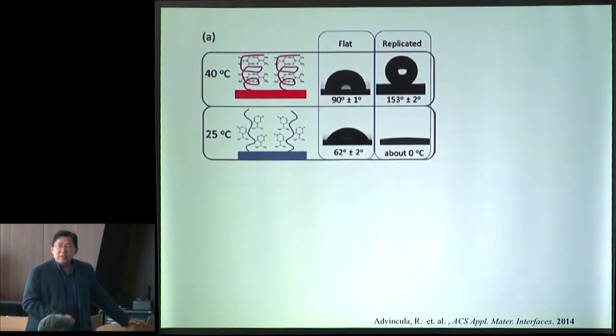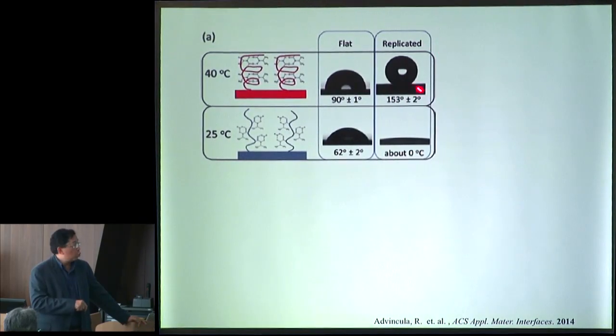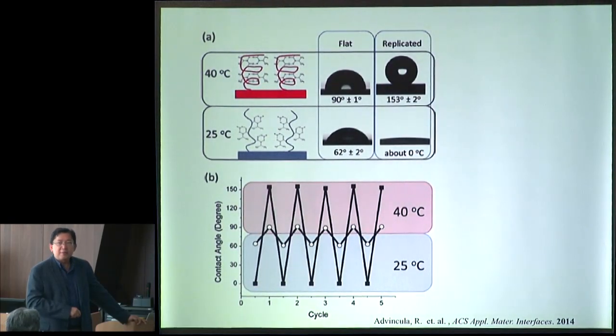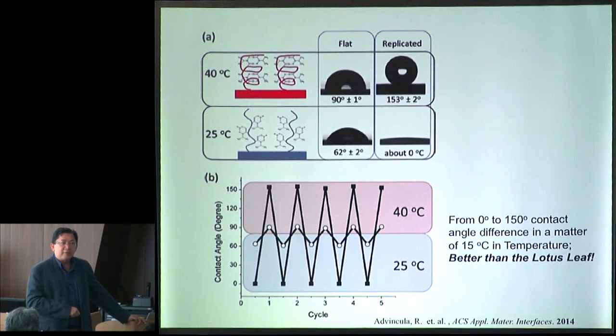Now the question is, how did the Lotus Leaf replica work? Well, the Lotus Leaf replica, when we cool it at 25 degrees C, completely wetted the surface, 0 degrees contact angle. And then when we heat it up with a difference of about 15 degrees C, 25 to 40, you have a dramatic change from 0 to 153, or what we call superhydrophobic. And not only this, this can be switched back and forth, back and forth, back and forth, simply by changing the temperature. So this is basically a Lotus Leaf replica that was improved upon by converting it into a stimuli-responsive polymer. Okay? So this is your second fake material.